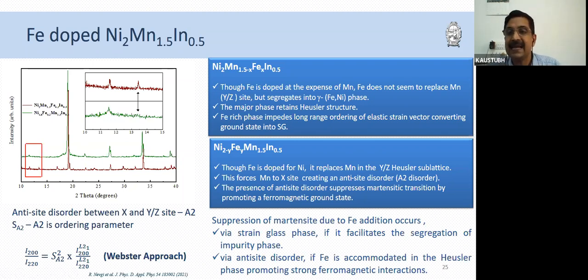So what we can say at the end of this first half is that the suppression of martensite due to addition of Fe can induce a strain glassy phase if there is a segregation of an impurity phase. Or if Fe promotes anti-site disorder, that means iron is accommodated within the Heusler lattice, and there is an anti-site disorder, then it will give rise to a ferromagnetic ground state. So it is not necessary that every time you dope an impurity, you should get a strain glass phase.